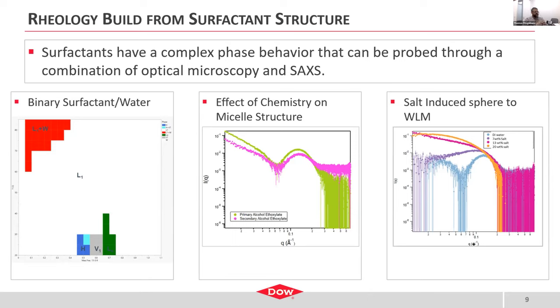So what I'm showing here on the right is the formation of a worm-like micelle in the presence of a primary alcohol ethoxylate, where the blue curve shows a scattering pattern very consistent with a spherical micelle. The purple curve, as it's moving up, shows a rod-like micelle. So it's not quite what I would consider a worm-like micelle, because we still have the ability to measure the length of the rod using traditional small-angle X-ray scattering. But as you get to a higher salt concentration, say in the magenta curve, you see not only the diameter of the rod, but then you see this longer range correlation and structure at low Q, indicating that you have transitioned from a spherical micelle to a rod-like micelle to a worm-like micelle.